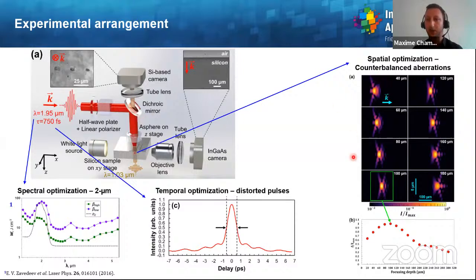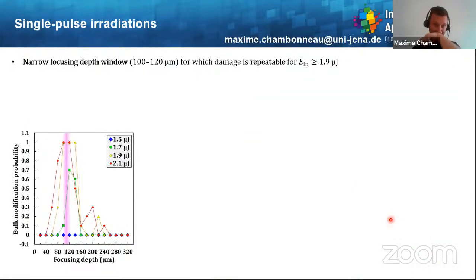And by doing some calculations with the previous model from my colleague Qingfeng Li, which is called InFocus, we were able to conclude that around 100 micron focusing depth, there should be some precompensation of spherical aberrations, meaning that the intensity should be maximum near this focus position. Okay, so what about the experiments?